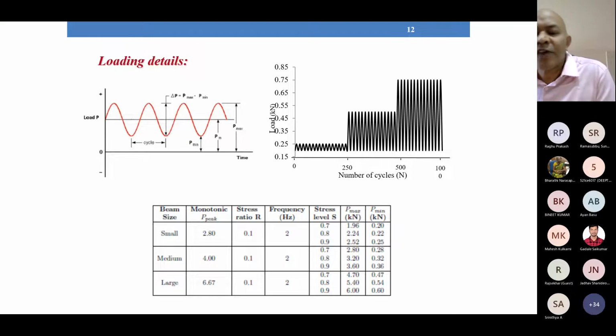These are the loading details. Initially we performed monotonic tests, that is, static tests under monotonically increasing crack mouth opening displacement, to capture the complete softening response. After the monotonic tests, we carried out fatigue tests. I would also like to mention that the number of researchers working in the area of fatigue of concrete is very few. People have worked in fracture, but under fatigue, it requires extensive experiments, which need testing machines and a lot of time. Some of these tests have taken almost 7 days continuously to failure, depending on the frequency of loading. So the number of people doing experimental work under fatigue is very few.